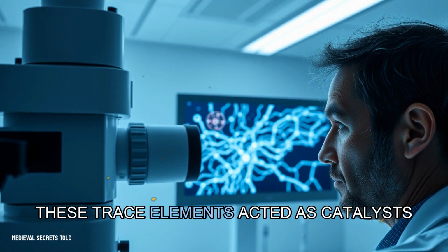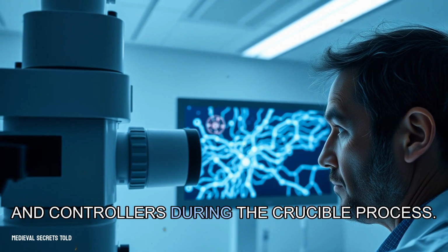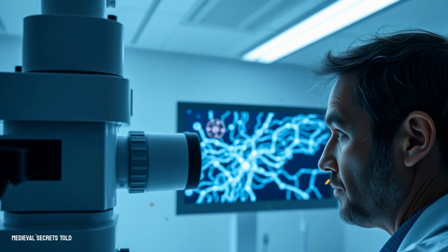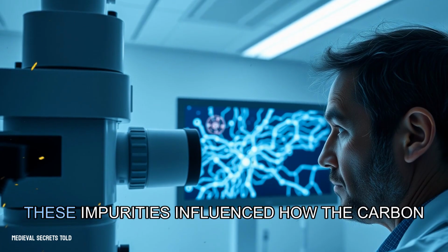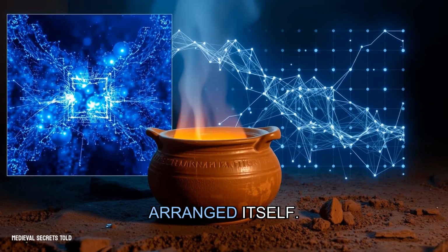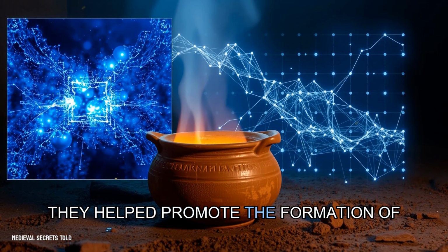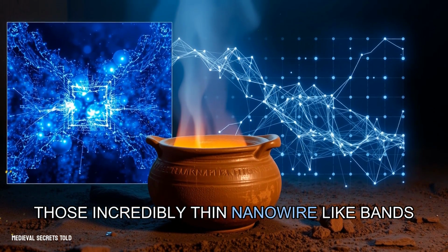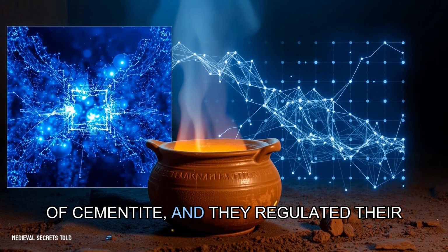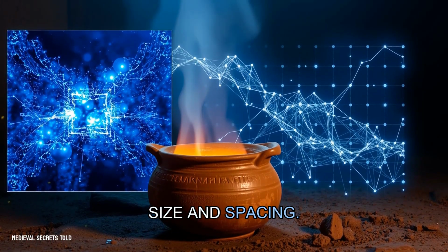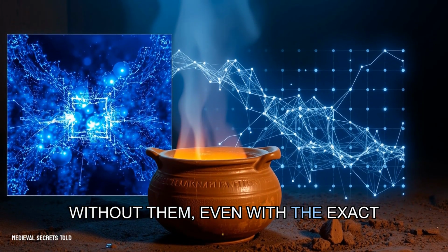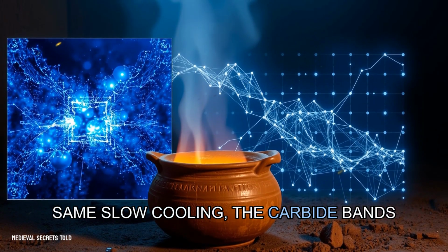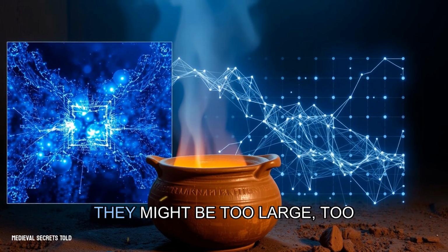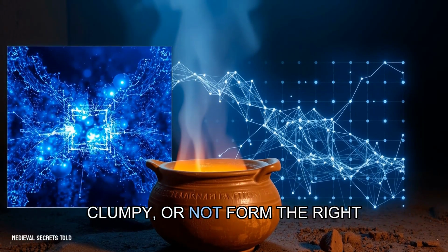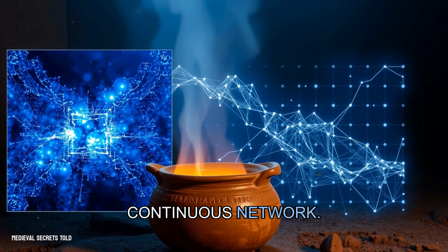These trace elements acted as catalysts and controllers during the crucible process. As the molten steel slowly cooled over days in its clay pot, these impurities influenced how the carbon arranged itself. They helped promote the formation of those incredibly thin, nanowire-like bands of cementite, and they regulated their size and spacing. Without them, even with the exact same slow cooling, the carbide bands would form differently. They might be too large, too clumpy, or not form the right continuous network.